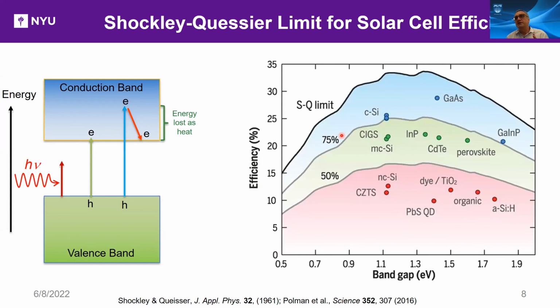So there are two competing effects. If the band gap is too large, then one does not absorb enough of the light. If the band gap is too small, then a lot of energy is lost as heat as you create more hot electrons and hot holes. So those two competing effects set up a maximum in the efficiency as a function of the band gap of the semiconductor. And that calculation was done back in 1961 by Shockley and Queisser.